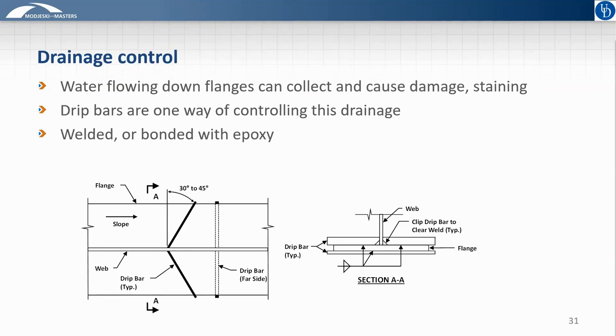So we've talked a little bit about water and keeping debris from trapping. Most bridges do have a longitudinal slope to them, and you get water flowing down the tops and sometimes the bottoms of flanges. And that can collect if allowed to deposit itself at bearings and other areas. And so one approach to controlling that is to use drip bars to control the drainage on the flanges, particularly the bottom flanges. There's some debate about the efficacy of this, but I certainly don't think they cause any harm. And there is anecdotal information that this does work.